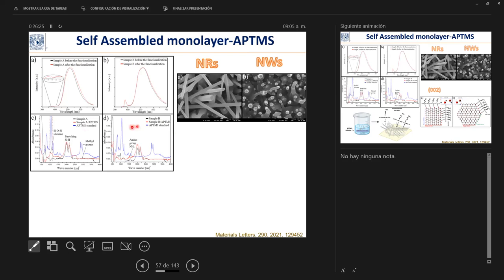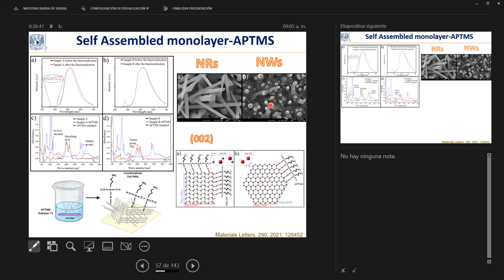So what we did in this work, which was published in 2021, last year, we grew nanorods. You can see here easily the difference. In this case, we have rectangular surfaces and nanowires, like always. We have gold on the tip, and then we have hexagonal parts. What we found is that these nanorods have a better photoluminescence response before and after the functionalization. And also in the FTIR spectra, the peaks, we found much more bondings in the case of nanorods.